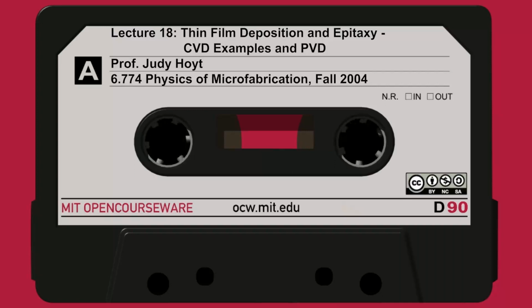Hydrogen would be less than 1%, maybe 0.5% or less in an LPCVD film, oxide film or nitride film, whereas in a plasma-enhanced film, it could be 10%. It could have a dramatic effect on the properties. And the stoichiometry of the film, LTO is not necessarily exactly SiO2. It could be SiOx, where x is slightly different from 2. Again, because you're not growing it thermally, you're depositing it.